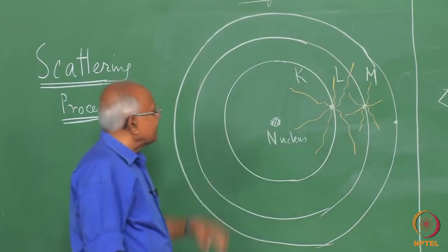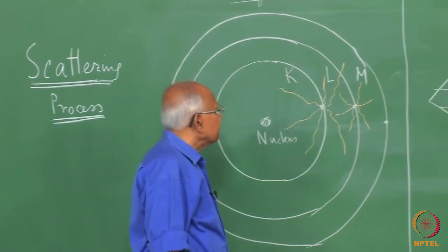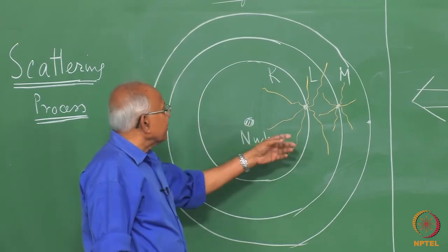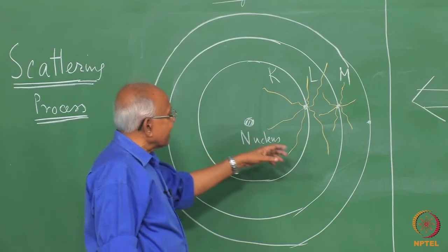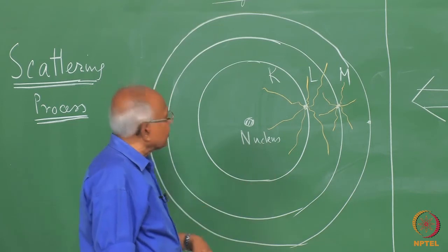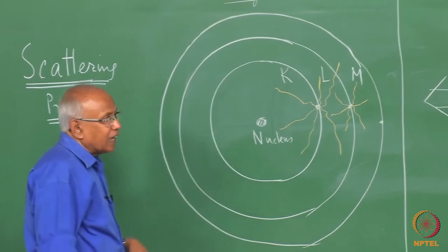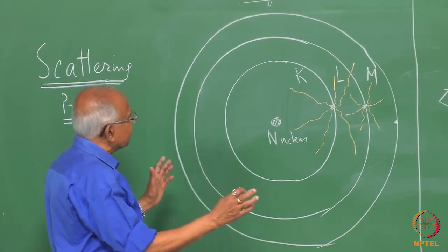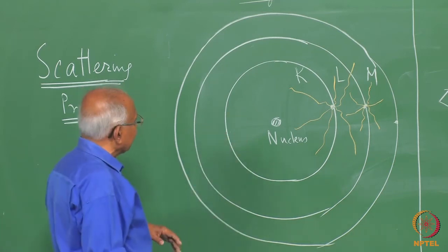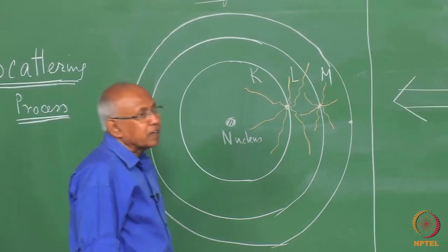So, this is the origin of the white radiation. The amount of energy which a particular electron in the atom of the target can take from the striking electrons will vary a lot, and as a result the wavelength that will be produced will also vary a lot. The totality of all the X-ray wavelengths coming out of the target material constitutes what is known as the white radiation or the continuous spectrum.